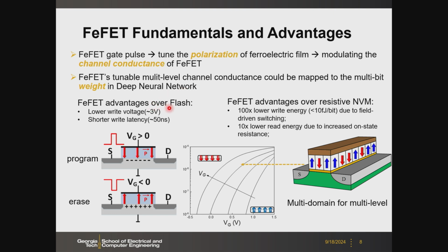Compared to the charge trap or floating gate flash transistor, the FE-FET could exhibit advantages like lower switching voltage and faster switching speed. Compared to resistive memories like RRAM or phase change memory, the FE-FET could have much lower write energy, because here you use a field to drive the polarization switching. This is like a transient switching. Unlike RRAM, which is current driven so you have to pass a lot of power, this one is field driven, which is why the energy is low.